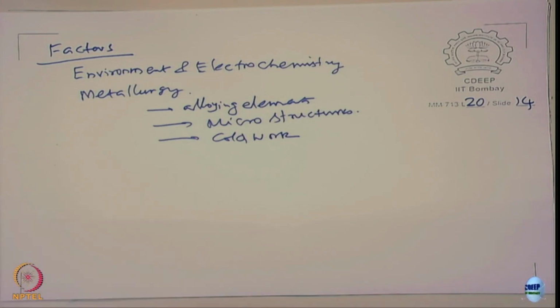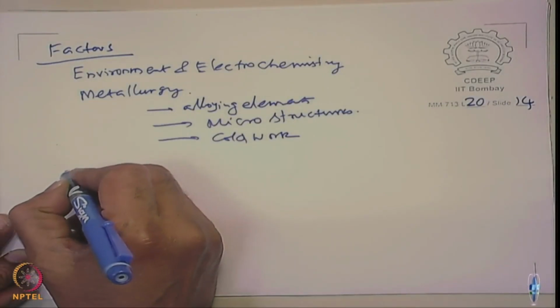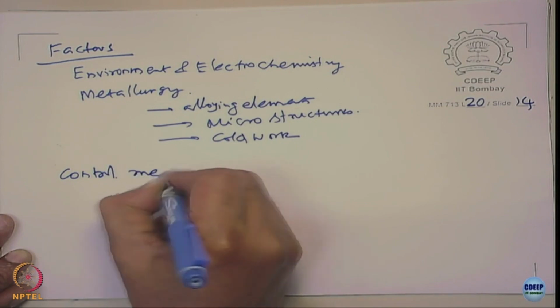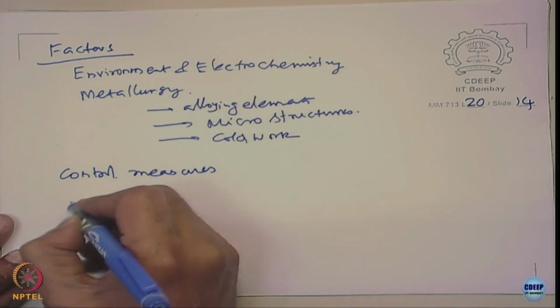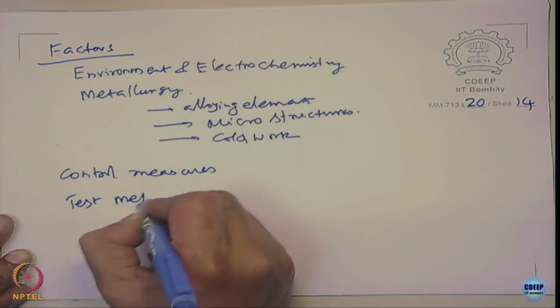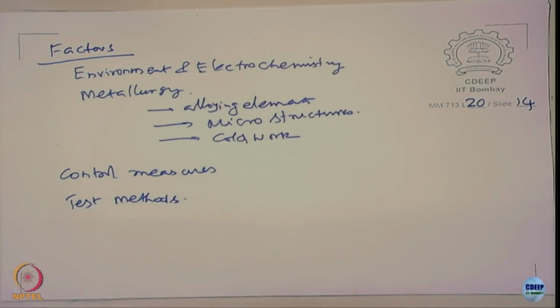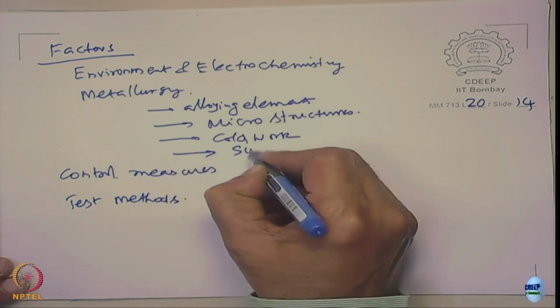Right. I forgot to summarize, right, and we also defined what is a pit, a pitting factor. It's not that any uneven corrosion can be defined as pitting, right. The radius of the pit to the depth of the pit is very important. The radius should be smaller compared to the depth of the pit. Then only the pit can be stable. Okay. Then we looked at what? Looked at the control measures. Then we looked at the test methods. Because you can add one more to this, and metallurgy is a surface state.